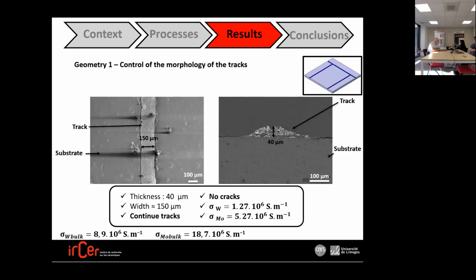The first geometry we made was to control the morphology of the tracks. As you can see in these pictures, we have deposited one track of tungsten, which has a width of 150 micrometers, on the top side of an alumina substrate. You can see the dimensions that we are able to have. We have controlled the continuity of the track. If we use tungsten, we obtain a conductivity of about 1.3 10 power 6, and if we use molybdenum, we can obtain a conductivity of 5.3 10 power 6. It's the bulk conductivity divided by 5, approximately.